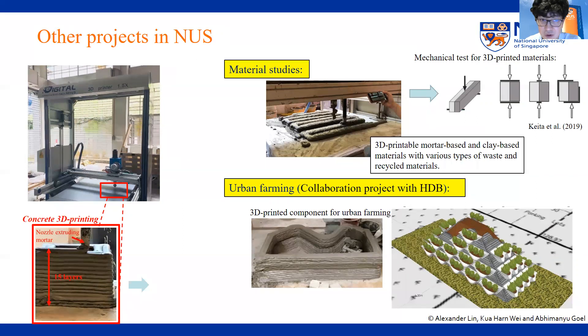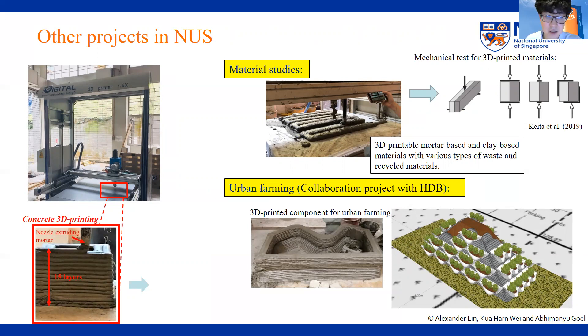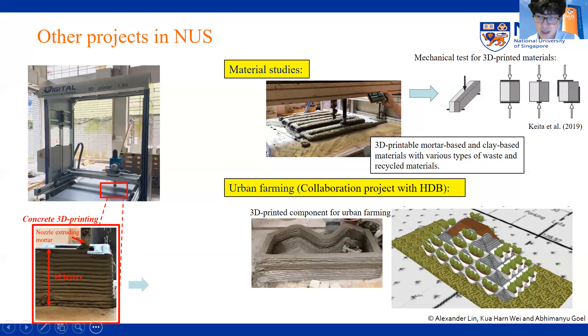Another of our research focuses is material study. We carry out various types of 3D printable mortar-based and clay-based materials where various types of waste and recycled materials are incorporated, including recycled plastic, which is actually relevant to the interest in India. We test the mechanical properties of these 3D printed materials and also their printability, including whether we can extrude them successfully and whether the material can maintain its shape well after printing.